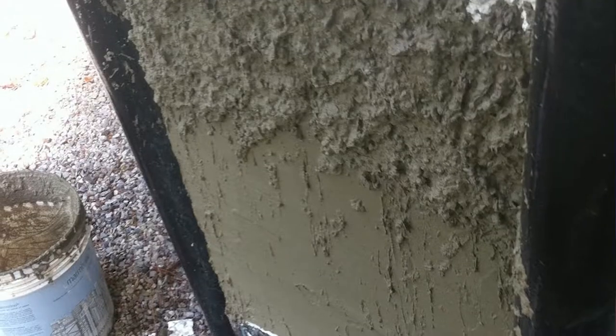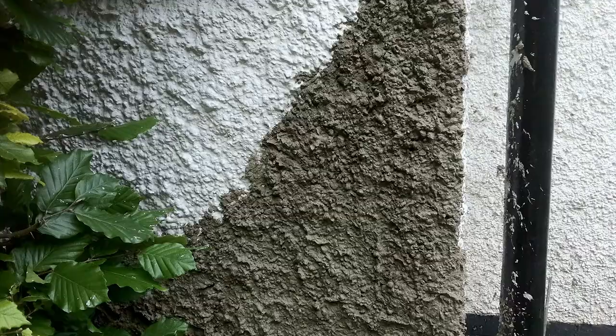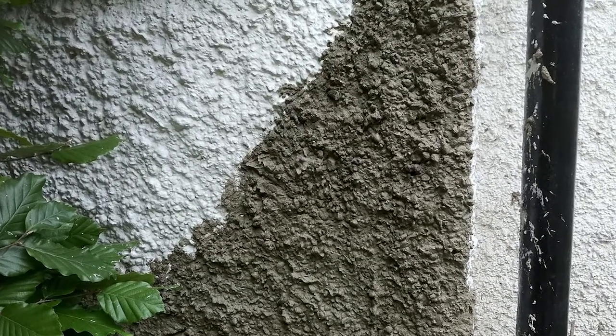This is done for a different reason. This is done in poor weather areas and colder climates, and it allows for more water to be absorbed into the outside of the building, allowing it to take a little bit more weather without any physical signs of damage occurring. There will be cracks, there will be water penetration getting in, but the stones help to absorb some of that and build up a little bit of a stronger barrier in really harsh conditions. These large stones used in dry dash or wet dash will absorb some of that. So that's the only real time when you'd go against the theory of reducing your grain size as you get to the finer coats.